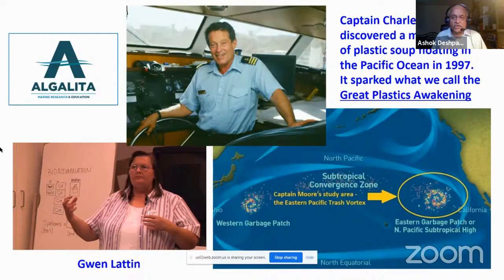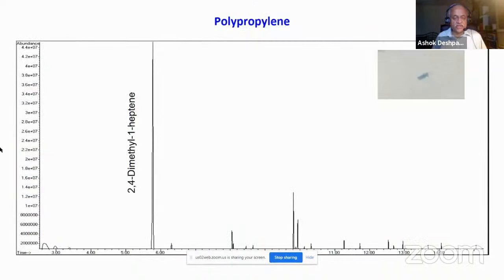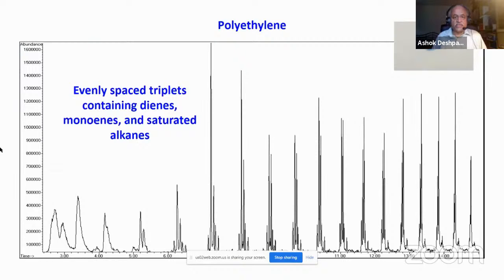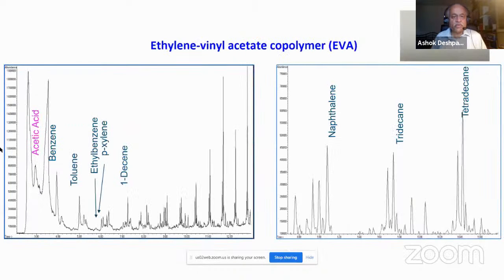Captain Charles Moore discovered a massive area of plastic soup floating in the Pacific Ocean in 1997 that sparked what we call now the Great Plastic Awakening. So Captain Moore and Gwen Latin provided us some samples of microplastics from the Pacific garbage patch. The first sample has signature of polypropylene. Second sample has signature of polyethylene. This sample is called ethylene vinyl acetate copolymer because it contains acetic acid and also has the signature of polyethylene. There are some additional peaks which we plan to analyze when we are able to go back to the laboratory.